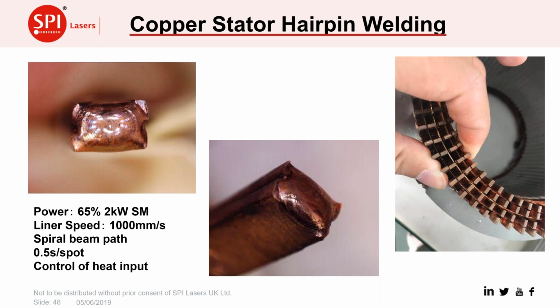What we're showing here is there's two kind of rectangular parts of copper. If you think about looking at that top picture, which have had an end on welds put together, which has joined together the two parts. Again, this is copper, so it's good to make a weld which is very low spatter, so that they don't get any debris around the rest of the motor. And by using the spiral, the oscillation welding, you can produce a very smooth weld pool, which joins the two parts together with a good control of heat input and not letting it go where you don't want the heat. So we can produce very good hairpin welding from stator parts.